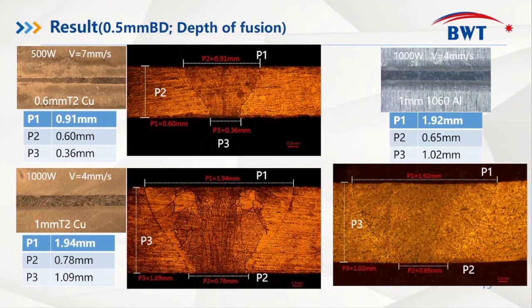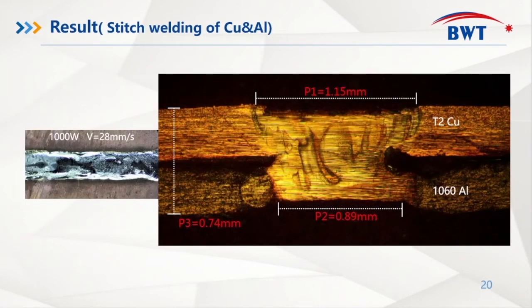We also performed welding tests on both copper and aluminum plates of 1 mm thickness. The performance of the blue laser was maintained well. Welding aluminum and copper together presents a challenge because of the large differences in absorption and melting points of the two materials. The blue laser shows a good result of switch welding between copper and aluminum. The power is 1 kilowatt with a speed of 28 millimeters per second.